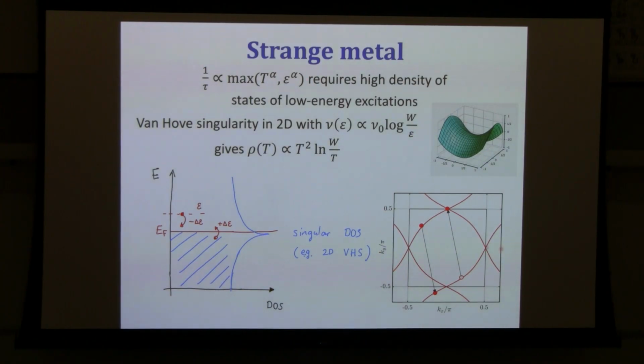So in particular, suppose that we start from an electron somewhere here. This is our excited electron. It can scatter into that state. And to conserve energy and momentum, we scatter an electron from the filled Fermi sea to the Van Hove point. But there's a lot of ways we can do this because there are so many states close to this hotspot. Okay, so if you do the calculation, it turns out that the electrical resistivity in this kind of situation goes like T squared times log of 1 over T, with some energy numerator.